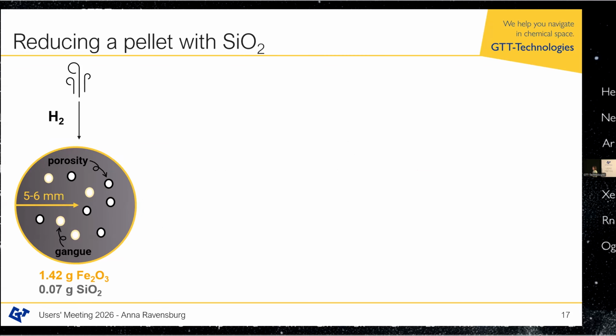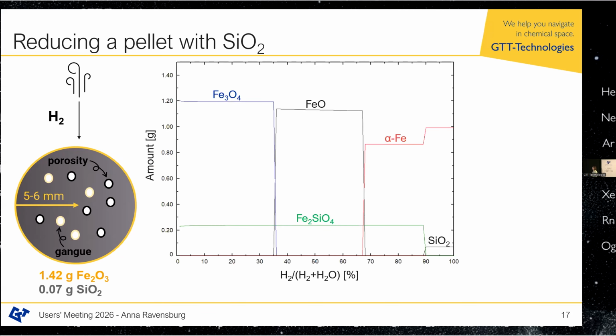If we start with SiO2, we have here a pellet with pure hydrogen reduction. It has some iron oxide and SiO2. And this plot you have already seen today. If I calculate it with FactSage, this is what comes out. For different H2 to H2 plus H2O ratios, I get different phases that are stable. Of course, the left side corresponds to a higher oxygen partial pressure, the right side to a lower one. So in the left side, I get Fe3O4 stable, and then I get to FeO. And alpha iron, so pure iron, which I need for 100% metallization degree, is only possible in the right side of this plot. So I need at least about 67%